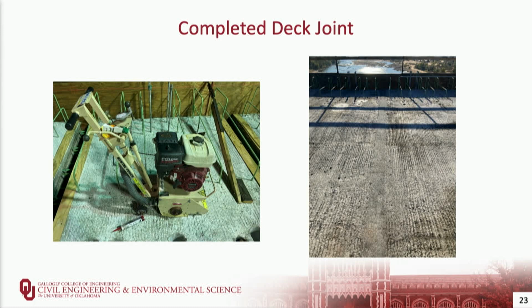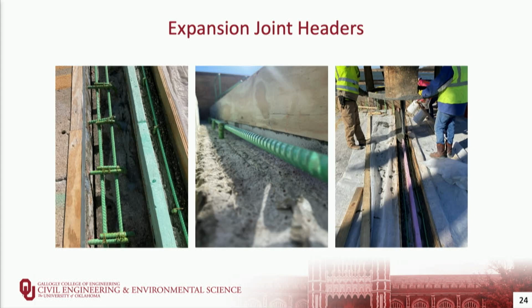Once the joints were completed and allowed to cure, they went back and ground those plane with the surface of the bridge deck. And if you look at that picture on the right, you can barely even tell that there's a joint between those two panels.